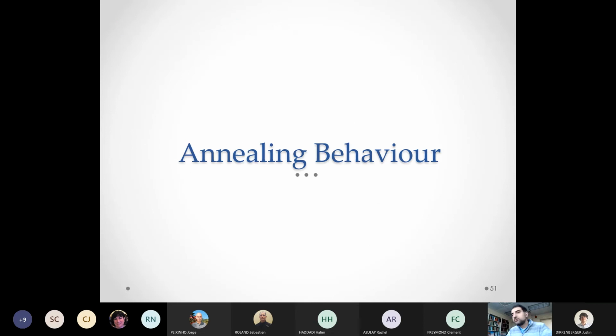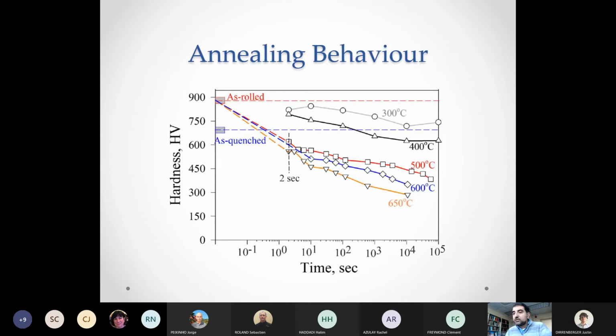So I will just take 5 more minutes to briefly show examples of what happens during annealing. As I mentioned, we're able to deform martensite to very large strains, which means we already have high dislocation density in martensite in the as-quenched state, and now we can deform it to a strain of 1 or a strain of 2. We should be able to achieve a huge stored energy within the martensite. So in this example here, we deformed to a strain of 1, and then we did different annealing treatments.